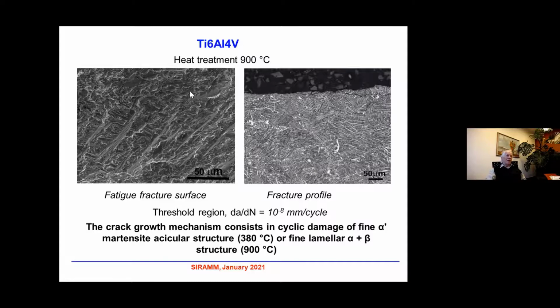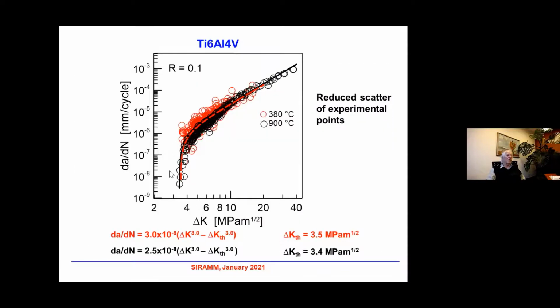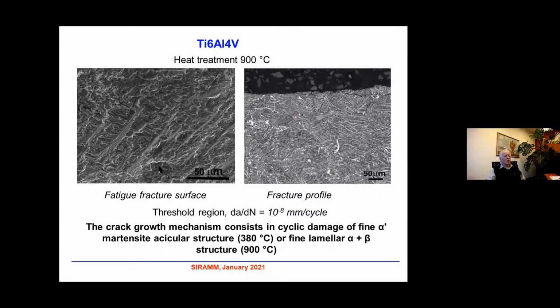In the case of heat treatment 900, again, the fracture profile is here. The crack is again flat and is running through the microstructure. However, in the threshold region here, with a crack growth rate very low, 10 to minus 8 millimeter per cycle, the mechanism is somewhat different. You can see these flat areas. The crack growth mechanism consists of cyclic damage of fine alpha prime martensite acicular structure at 380, and it changed to damage of fine lamellar alpha plus beta structure at 900 centigrade. Nevertheless, there is practically no influence on the threshold values, so the mechanism seems to be a little bit different.